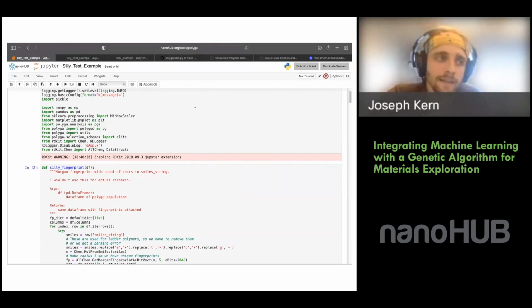Whereas with an inverse design algorithm like PolyG2G, you have to train a model that has those criteria already defined. So if I want to change my glass transition temperature target to 500 Kelvin to 600 Kelvin, I have to retrain the model completely to actually do that. For PolyGA, I just change the fitness function a little bit.